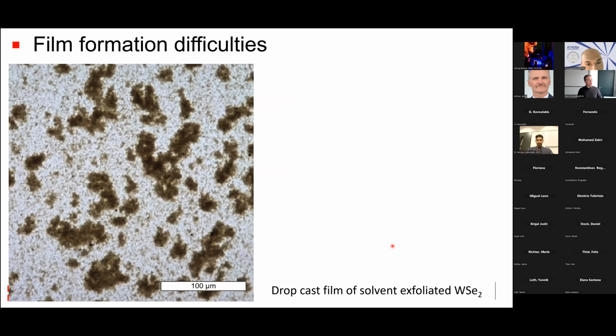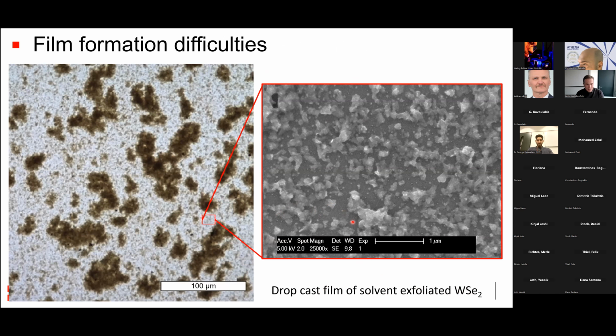Here's an optical image of a film that we made by just drop casting some exfoliated tungsten diselenide. You can see these big aggregates by SEM, perhaps more clearly. The issue here, of course, is that our semiconducting basal plane is not in good contact with the transparent conducting substrate, meaning that we have very, very poor performance. We tried many different techniques to optimize the deposition of these nanoflakes, including floating the film at a liquid-air interface, which still didn't work.